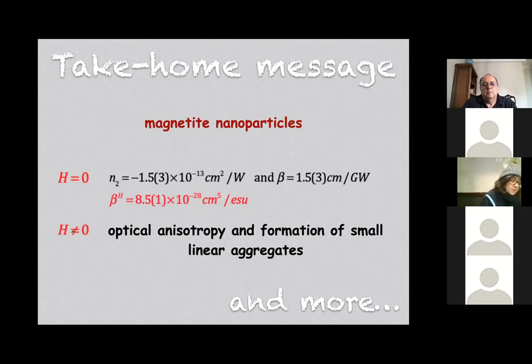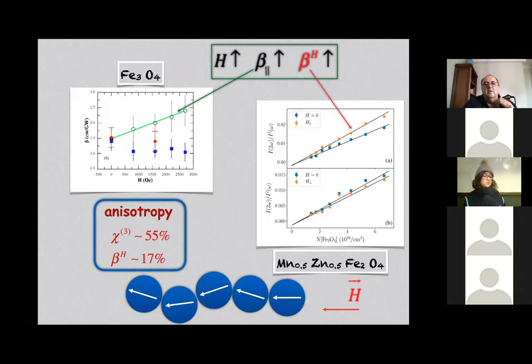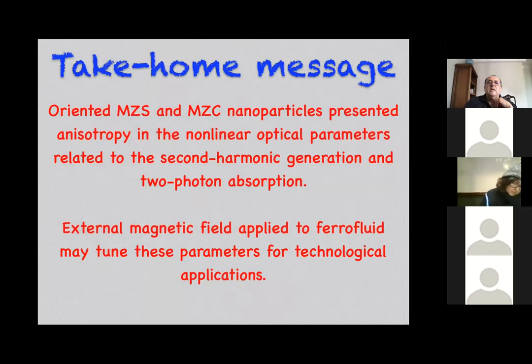When you put the external magnetic field, there is a formation of small linear aggregates and the anisotropy comes. So increasing the magnetic field, we increase the absorption along the direction parallel to the magnetic field, but in the direction perpendicular, we have almost no difference. And also here, in the case of the spherical or cubic particles. So these are basically the take-home message.